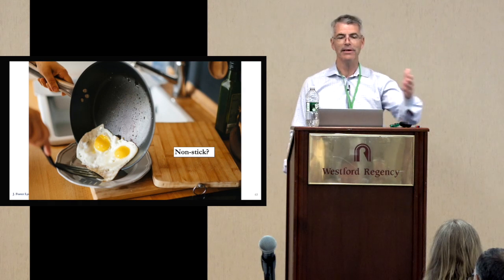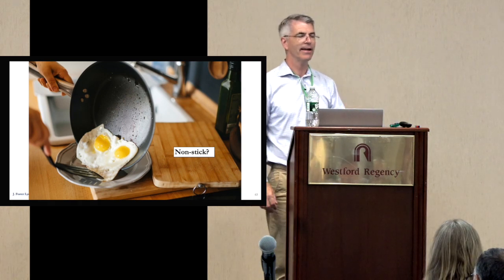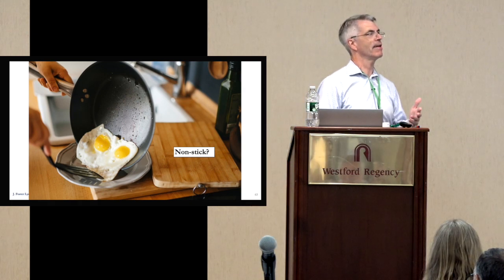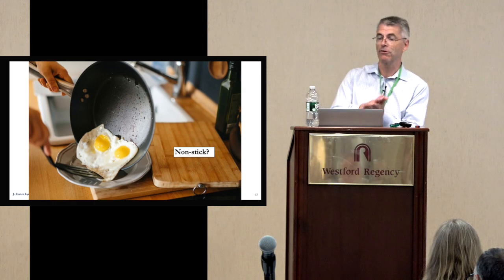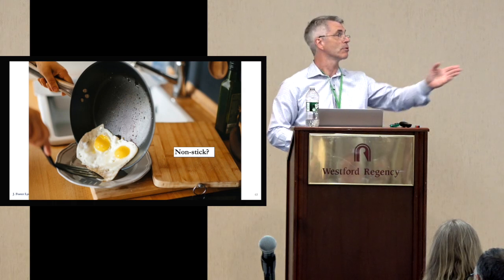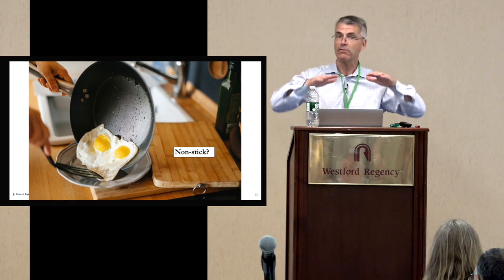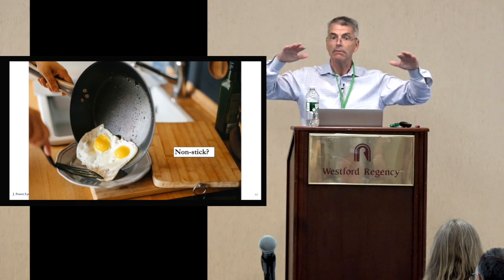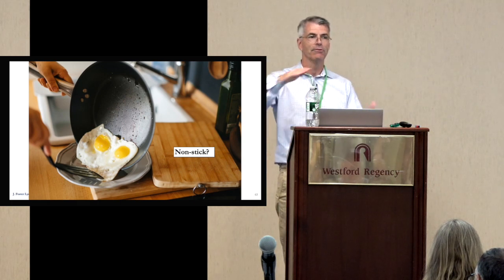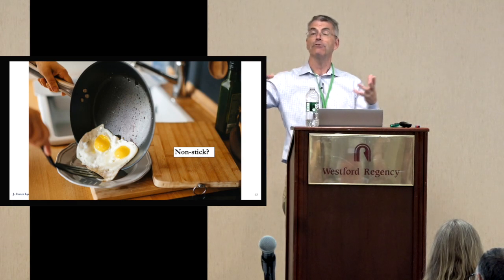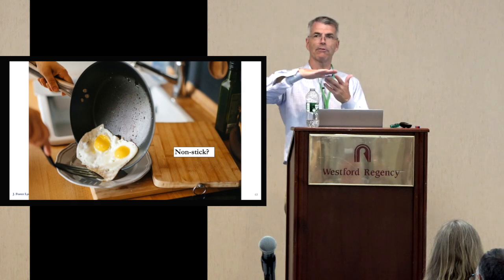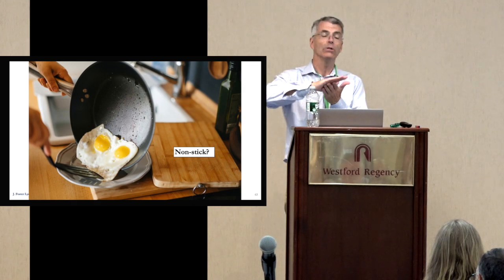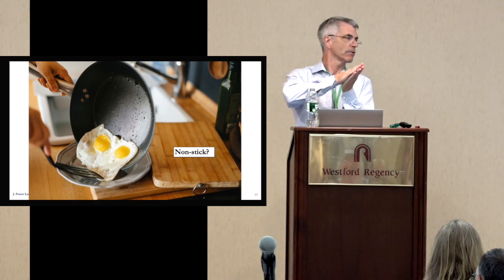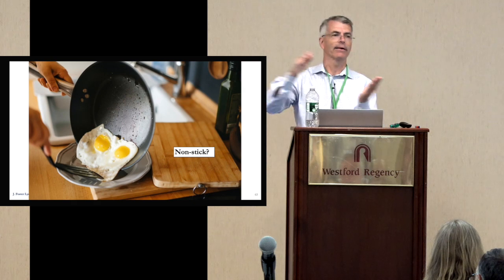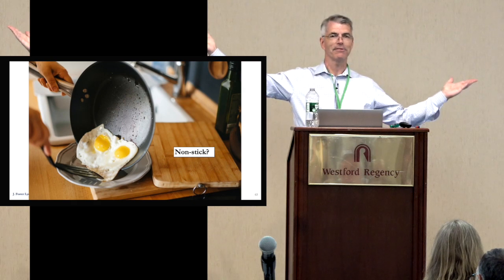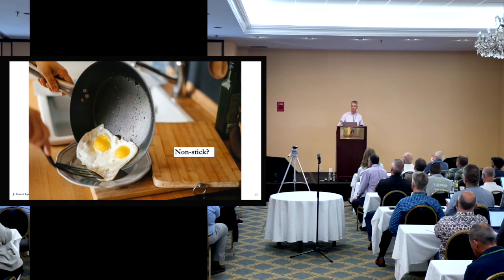But it's not impossible to stick to a non-stick pan. But without intermingling and without entanglement, things don't really stay stuck. And the surface of the pan isn't optically smooth like the gauge blocks. They're always a little bit rough, right? So that little bit of roughness, and the fact that you have only very weak surface bonds, makes it very easy to start and propagate a crack. So stuff just doesn't stick to it. Keep that in mind.